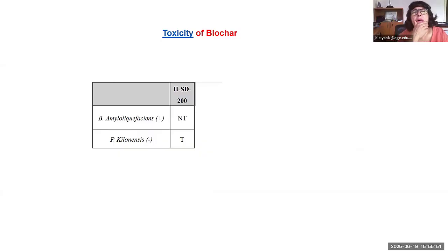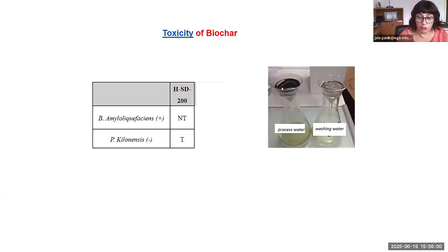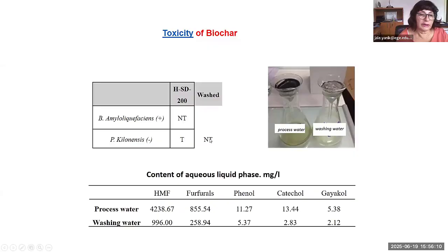To investigate why it is toxic, we washed our biochar with water, and after washing, we again controlled toxicity and it was non-toxic. And we can say that some compounds remaining on the biochar led to toxicity, because in wet carbonization, the carbonization takes place in aqueous solution, in water.